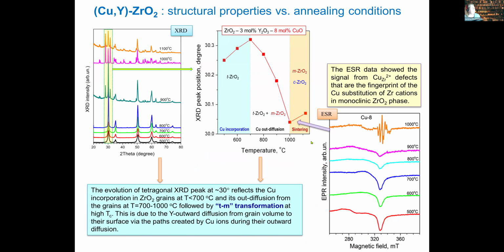In our previous research we concentrated on yttrium and copper co-doped zirconium oxide. The aim of that research was to produce powders for catalysis. Saying in advance, we got good catalytic activity, but there were a lot of efforts to get insight into the incorporation of copper, its interaction with yttrium, and the effect of annealing temperature on the structure and other properties of these materials. Usually we use different structural characterization like X-ray diffraction and electron spin resonance to get information about the crystalline structure and about surface complexes on the grains of zirconium oxide.